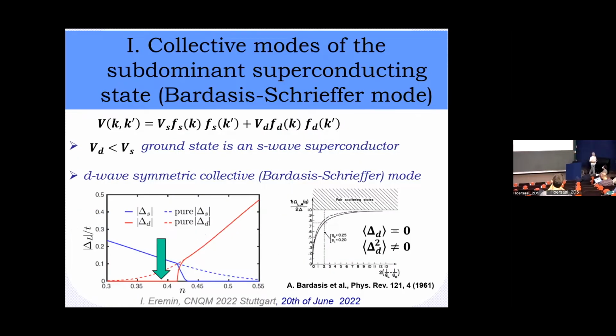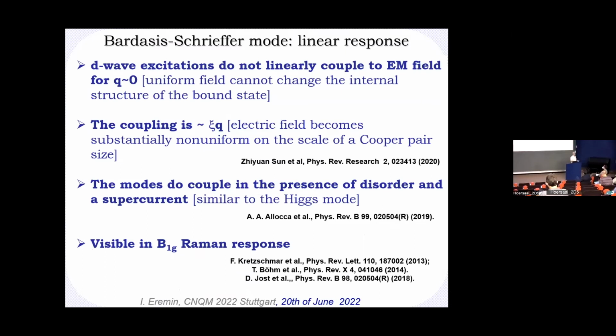So let's try to see whether in the third harmonic generation you excite immediately this type of mode, which has the name of the Bardasis-Schrieffer modes. And the simplest example of it has been considered by Bardasis and Schrieffer, where you start with the effective pairing interaction, which in the tetragonal system can be decomposed into the S wave and D wave, and you take a situation where the S wave, which would be in this case an extended S wave, is dominating, and you have an S wave ground state, but the D wave is nearby, and essentially you have a region near the transition between S and D wave, where you expect a sizable D wave fluctuation in an S wave superconductor.